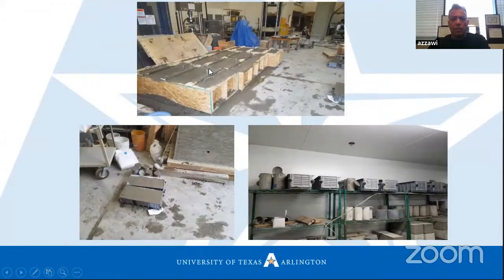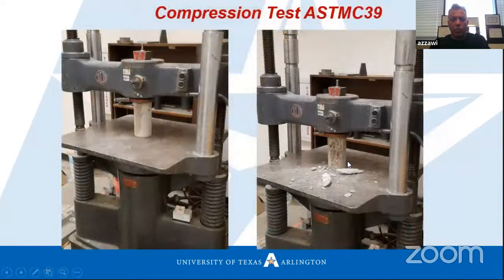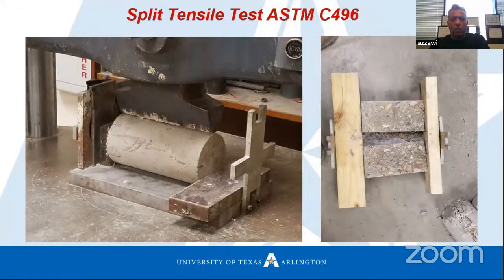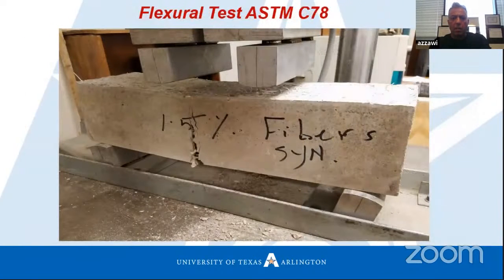After finishing the casting of our samples, we stored them in the curing room. After 2 days, 48 hours, we remove the formwork, then we store them in the curing room. After 28 days, we start doing tests. We start with the compression test, as we see, based on ASTM C39. We also did the split tensile test based on ASTM C496, and also the flexural test, as we see here.